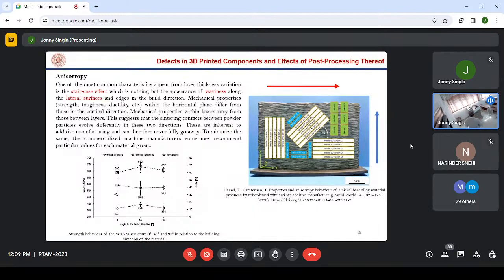But it is not possible in case of AM components. That is the inherent part of additive manufacturing: you will get directional variation of the properties. If you take samples in these three directions, you will get different values of the mechanical property. So this is called anisotropy, and it is inbuilt in AM. You cannot avoid it, but you can minimize it, right? And you can choose the direction which gives you the maximum value, and make your specimen, your component, from that direction, right?